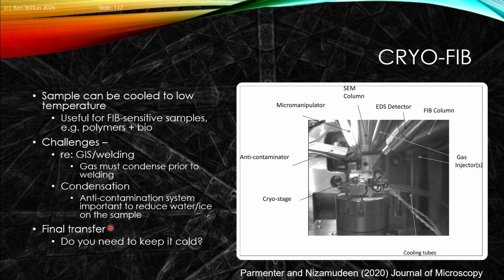In addition to doing this stuff all at room temperature, we recognize that there are certain reasons why we might want to perform our preparation using a cryo focused ion beam. Some of the simpler cryo systems effectively have a cryo stage, where we can now have the cryo stage that has cooling, typically through, for instance, flowed liquid nitrogen, to enable you to cool this stage downwards and cool the sample. When we do this, we want to reduce effectively condensation on the sample, so we tend to also include an anti-contaminator system, and we might also do some clever tricks with the micromanipulator as well as the gas injector